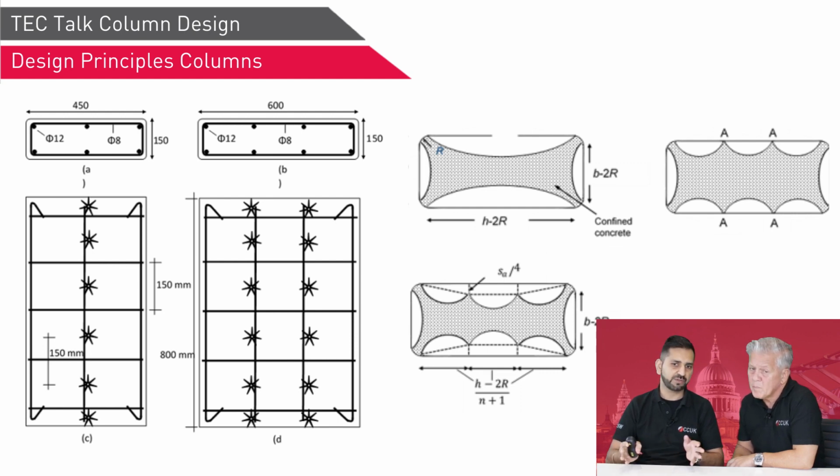So as soon as your corners try to push out, these anchors become active, and they act as a tie. So they will stop the FRP from pushing out. And that's how the confinement works much better in these instances. So this is the way we can do higher aspect ratio strengthening. We can apply the FRP as standard confinement, but we have to use these through anchors as a tie, so that the confinement at the longer edge will remain effective throughout.